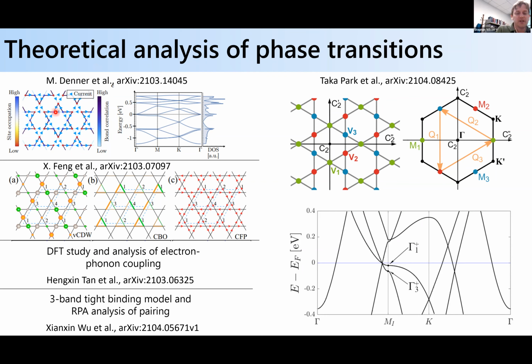There have been proposals for a couple of different types of flux states that could emerge and generate this anomalous Hall effect by breaking time reversal symmetry, derived from nesting born from the saddle points of these systems. Similar to this, Leon Valence's group here at UCSB has been looking at the types of charge density wave states you can realize from this 3Q order, doing a Landau analysis and renormalization group theory. Again, there are two saddle points near the Fermi level in their DFT models.